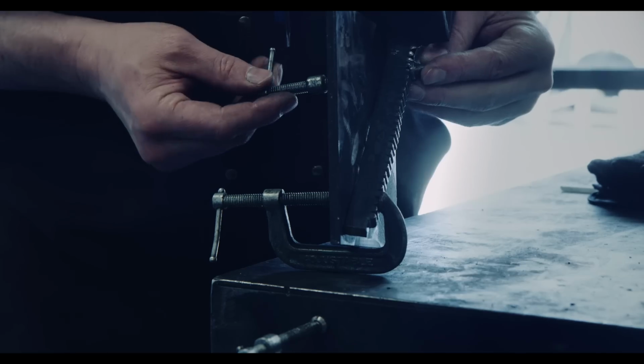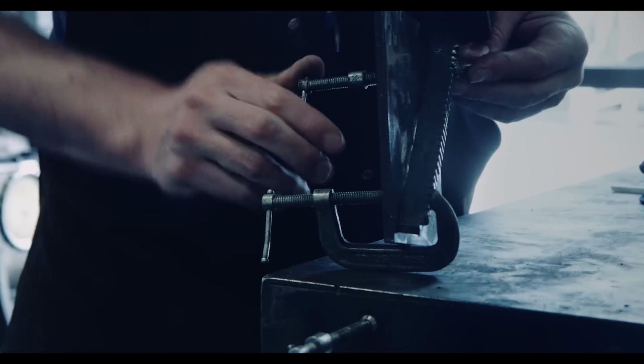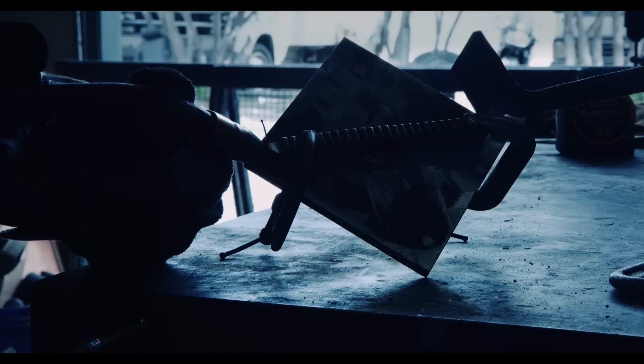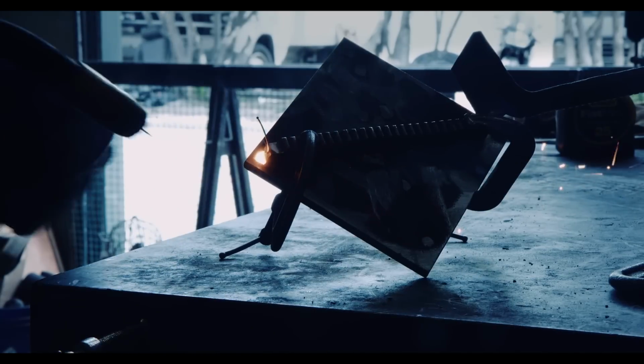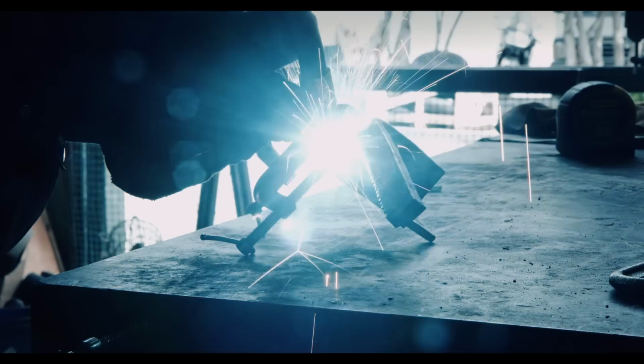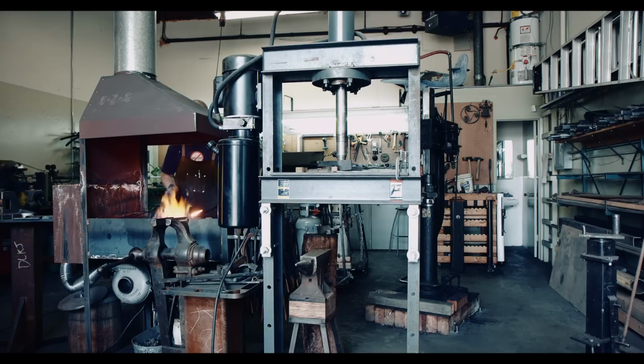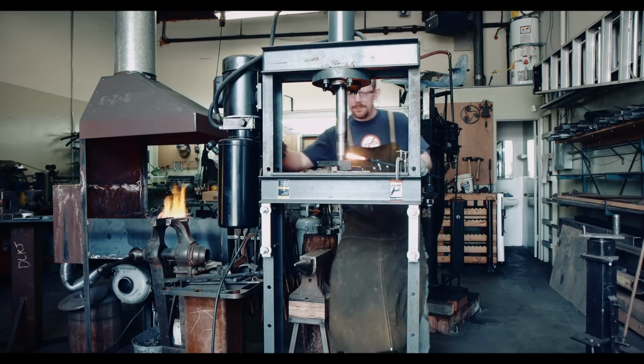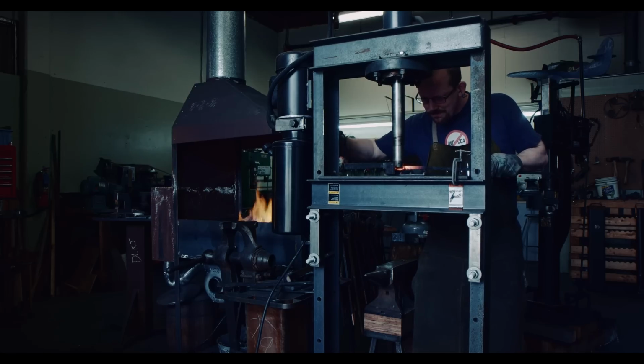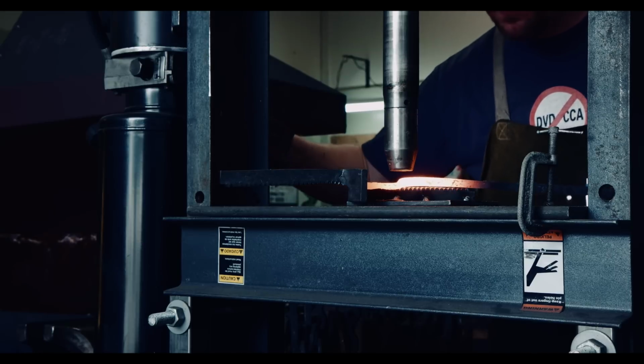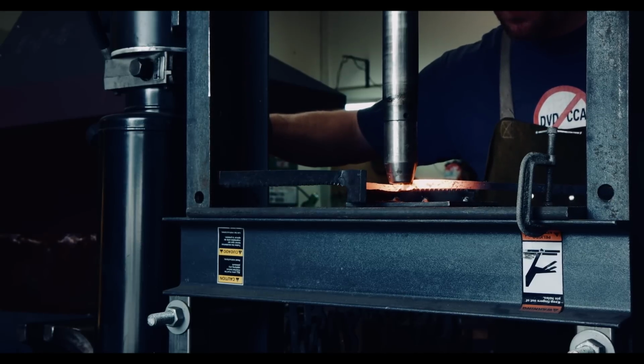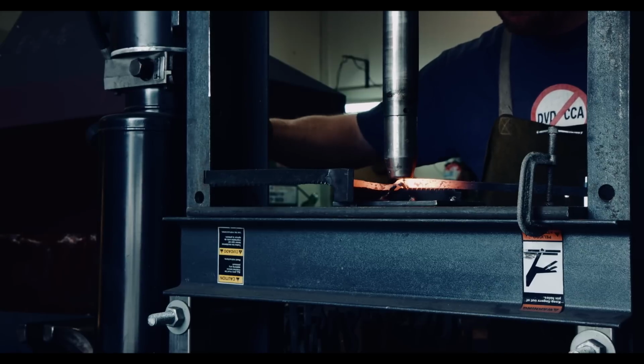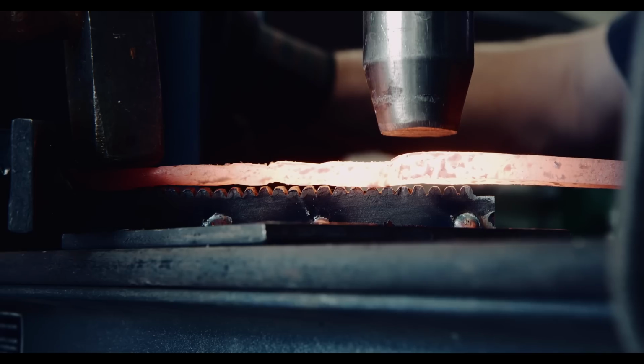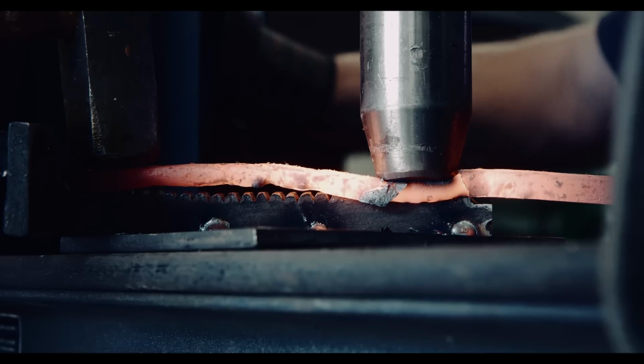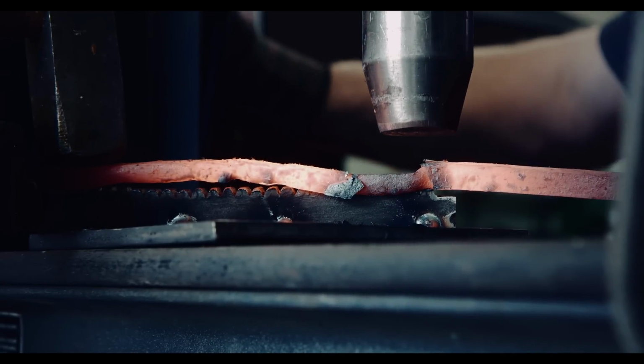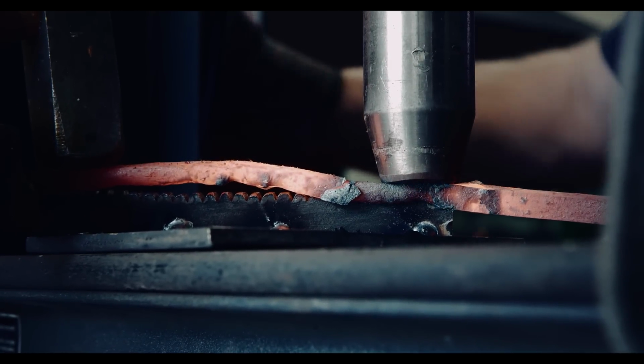What you see now is my method that allows me to do all the operations by myself. For the spearhead, I fortunately had Tony's help, so could have tried to do this differently. However, this is the way that I found that works for me. The basic idea is to take wrought iron, which is very soft when hot, and use the cold high carbon steel as the form into which to fit the wrought iron. Even when using a hydraulic press, this is still a little bit of a struggle, and Tony is helping to hold down one side of the wrought iron strip with the hammer.